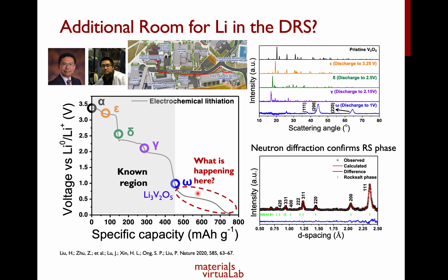Okay, so what this means is that it has a slightly higher voltage than your graphite anodes, which makes it less prone to lithium plating. But yet it is still much lower than your lithium titanate, which is 1.5 volt. And so it still has very high energy density, right?